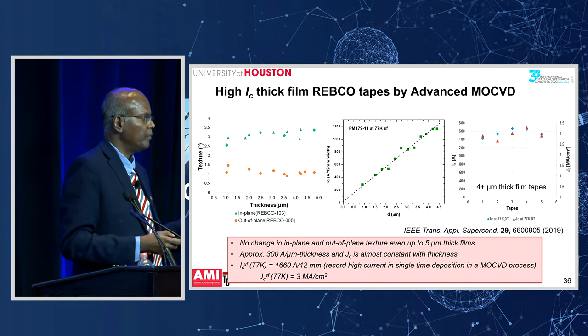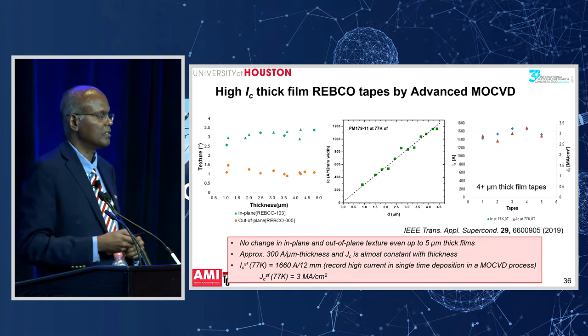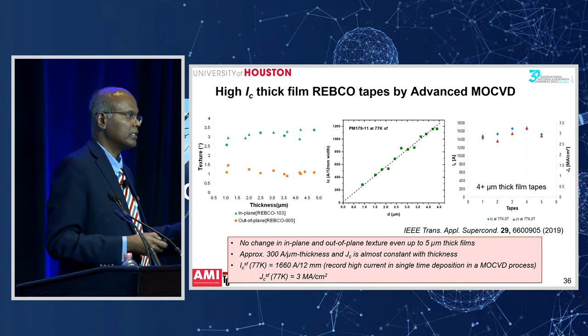So what we're able to make in a 2 micron film, now we can get in a 4 to 5 micron film. So we can get much, much higher current than was possible. All right? So that is improving the thickness to get the higher current. But there's also another knob to turn, which is that you can improve the pinning centers. Right? You can improve the pinning centers.